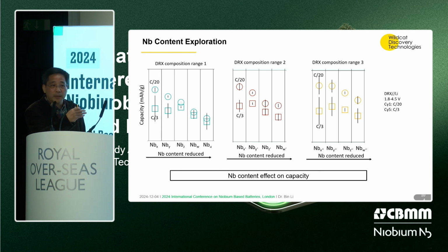There are so many things in play. So in this here, from the left to the right, niobium amount is reduced. And here we have C/20 capacity and C/3 capacity. You can see the capacity decrease significantly when you reduce niobium amount. And no matter what range you're playing with the DRX, you still see this trend. So when you don't have enough niobium, you will not get high enough energy density.